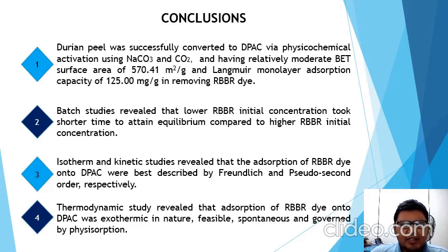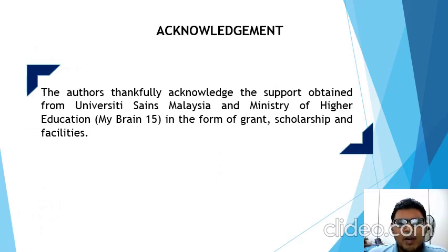Lastly, the thermodynamic study revealed that the adsorption of RBBR onto DPAC was exothermic in nature, feasible, spontaneous, and governed by physisorption.